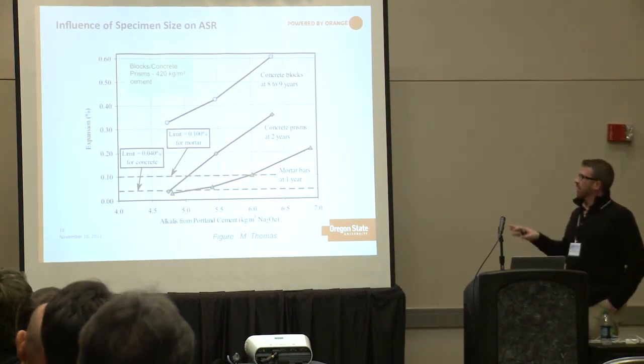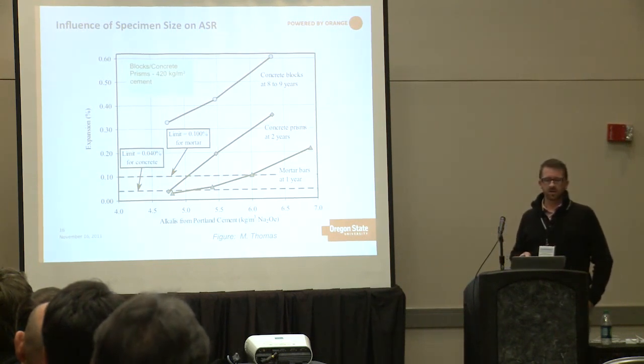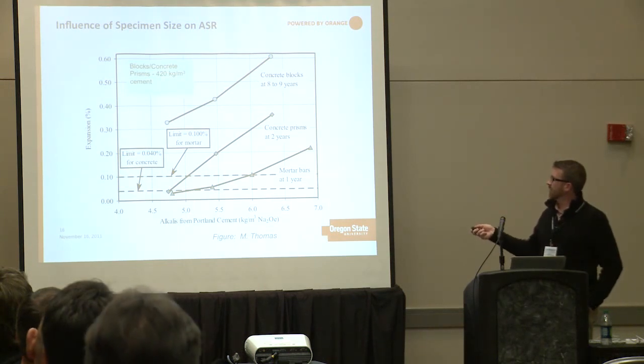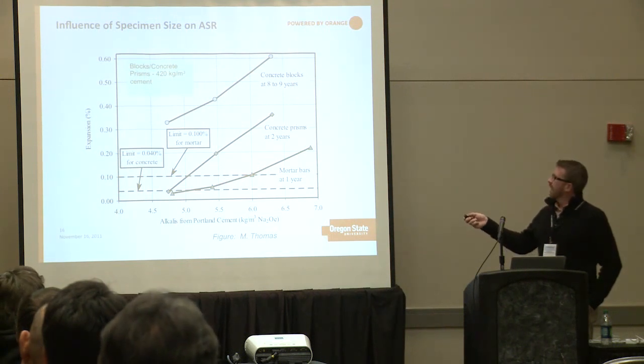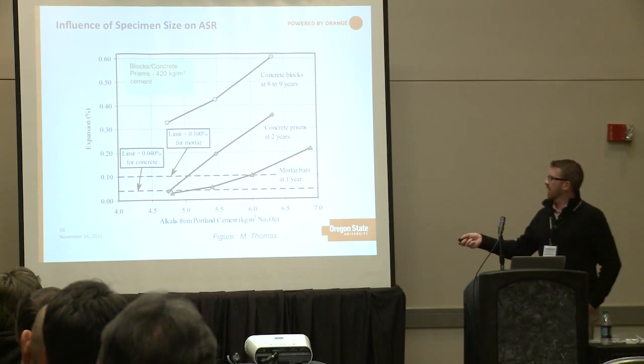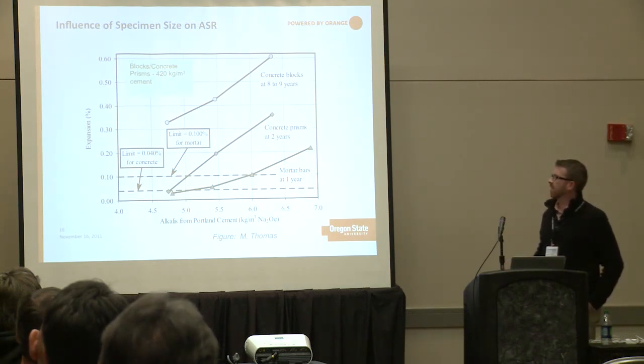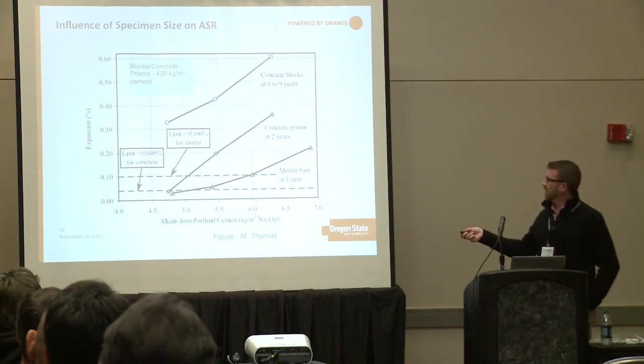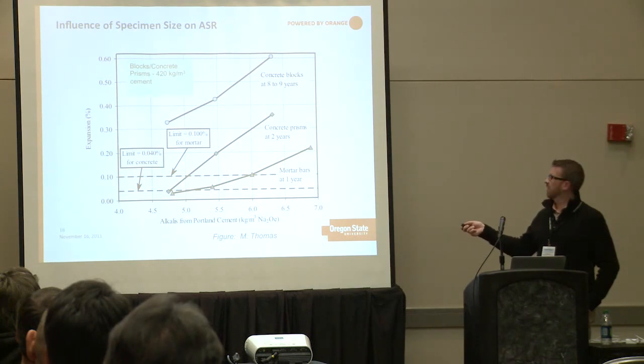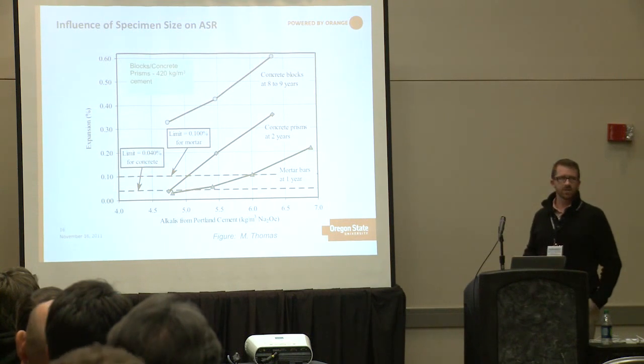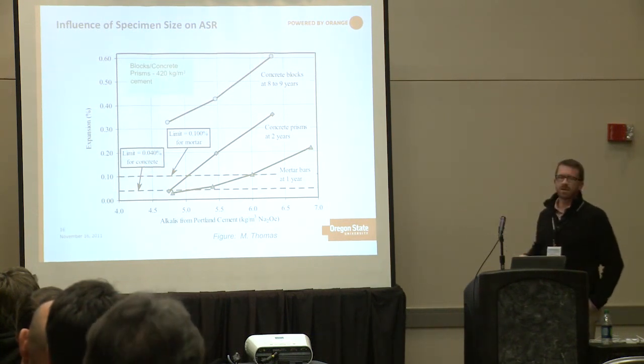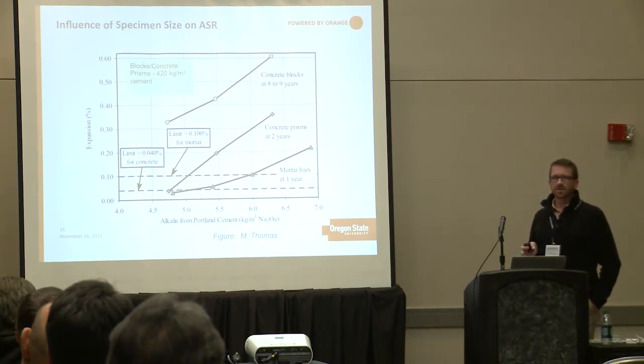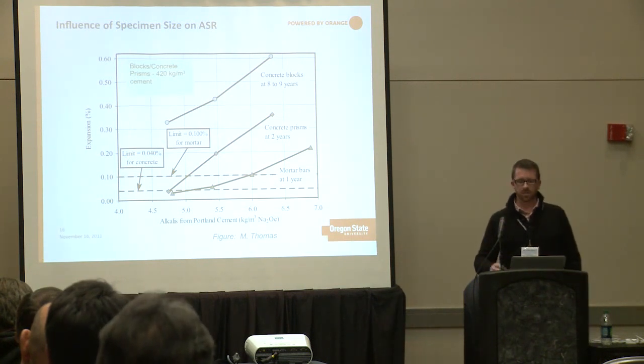This graph illustrates the importance of specimen size on alkali-silica reaction. The lowest line shows mortar bars — one-by-one-by-eleven-and-a-quarter-inch prisms — then concrete prisms, then larger concrete blocks. With alkali loading on the x-axis and expansion on the y-axis, to pick up reactivity in smaller specimens you have to reach a higher alkali level due to leaching. With larger specimens where leaching is less pronounced, we see higher expansion occurring earlier. Leaching is a real problem in accelerated laboratory tests — we need larger sizes or increased alkali loading to pick up the potential for reactivity.